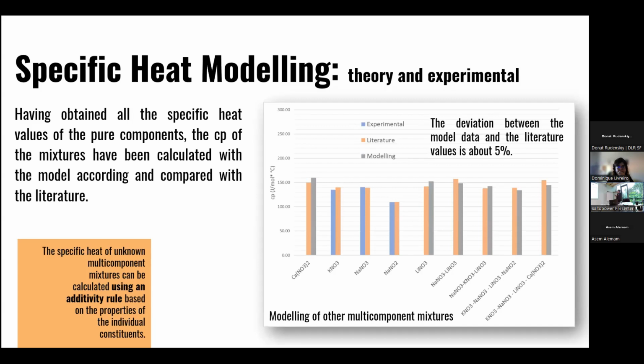So I reported again some experimental data, literature data, and our modeling, and as you can see, the deviation between the model data and the literature values is about 5%. So we can state that this approach can be very useful to determine the heat capacity of an unknown multi-component mixture without doing a lot of experimental